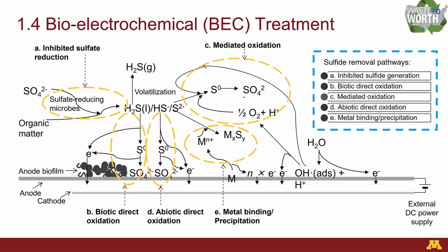So here I listed 5 possible pathways for sulfide removal during the bio-electrochemical treatment. It combines the activities of microbial and also electrochemical reactions. The first one is that during the BEC treatment, the sulfate-reducing microbes will be inhibited a little bit. Second, the biotic direct oxidation: the microbes inside the anode biofilm will be involved in the sulfide oxidation. The third way is the mediated oxidation assisted by the oxygen generated through anodic oxygen generation. The fourth way is the direct or abiotic oxidation assisted by the anode itself. And the final way is metal binding or metal precipitation.